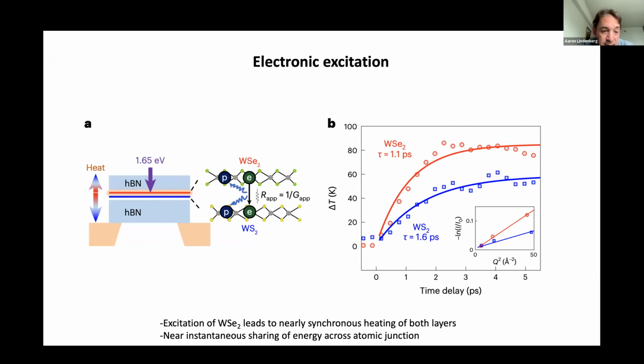We said, all right, now let's repeat this experiment again, but now we remove this top metallic layer and we directly electronically excite the WSe2. So we're coming in with a 1.65 eV excitation. This is above the gap, essentially resonant with the first exciton peak for WSe2. It's below the absorption edge for WS2. So all of the energy is selectively deposited in this top layer of this atomic junction. And then the question is, how is energy shared, again, between these two structures?